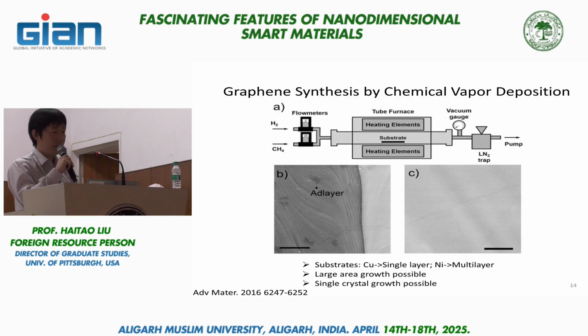On the bottom are scanning electron microscopy images. On the left hand side, you see this dark side is the copper substrate coated with nucleation sites of graphene. You see this small triangle, and that's a signature of graphene nucleation sites because of the inherent crystal symmetry of graphene, which is 6-fold and 3-fold. So you see this nucleation growth of graphene domains on the copper. On the right hand side, it's really hard to see here, but you see a very faint line across the middle of the image, and that shows the boundary between a graphene flake and the absence of graphene.